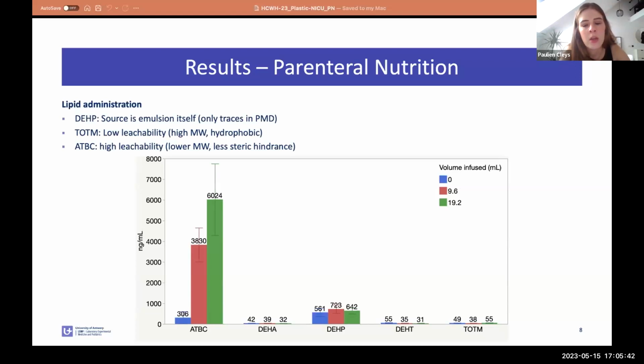And here we focus on the lipid samples since the detection frequencies in the non-lipid samples was quite low, so there we don't see any clear leachability patterns. So I will go from left to right, starting with ATBC, which is an alternative plasticizer, as we saw 2 slides ago, used in various medical tubing, showing significantly higher migration potential compared to the other alternative plasticizers. And this could be due to its lower molecular weight or a smaller steric conformation compared to the other compounds shown in the slide.